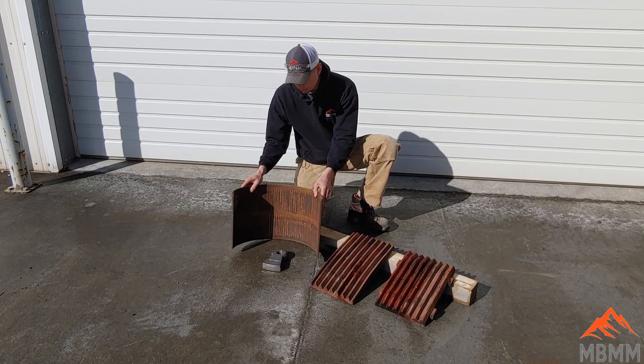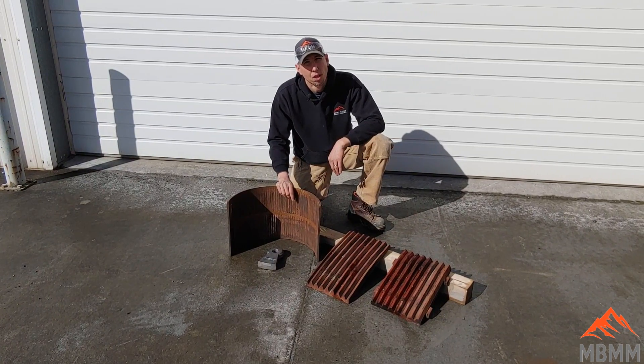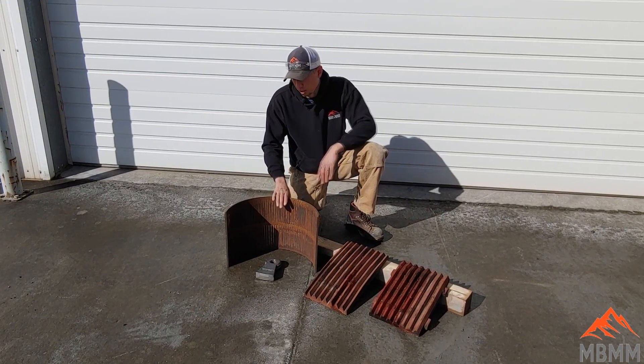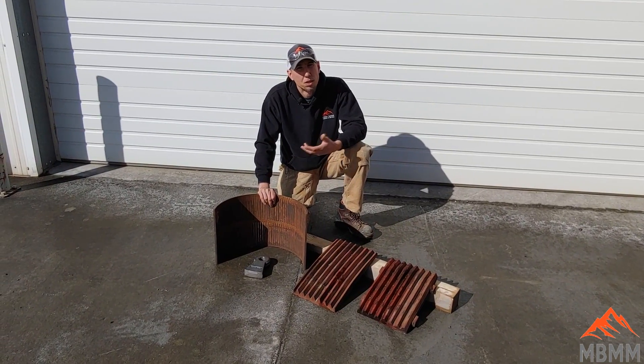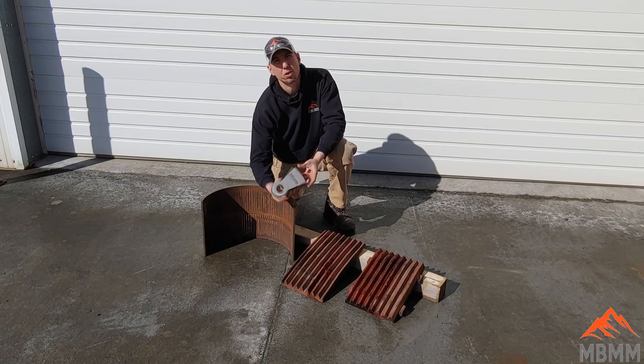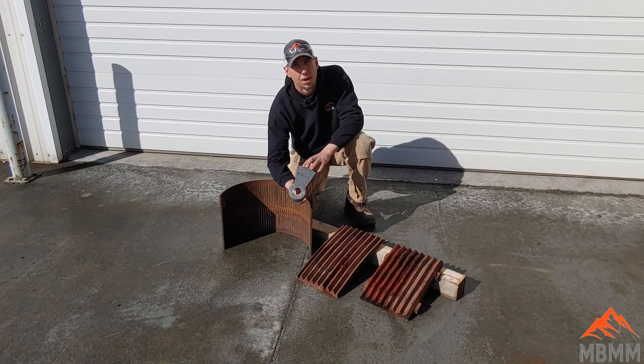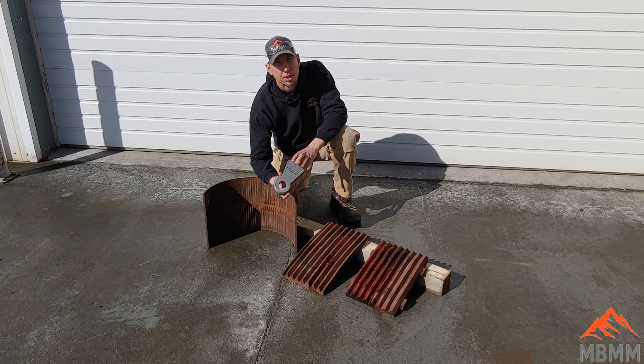This is one of our screens for our 16 by 12 hammer mills — these are laser cut slots. This particular screen is a 1.2 millimeter slot, and for typical quartz ore you get 70% of your material passing a 20 mesh screen. We also have a smaller 0.8 millimeter screen, which gives typically about 70% passing a 30 mesh screen. This is one of the hammers used in both our 16 by 12 and 24 by 16 hammer mills — a high chrome hammer, which allows for a much harder and better wear surface. In the 16 by 12 we use 20 of these hammers, and in the 24 by 16 we use 24 hammers.